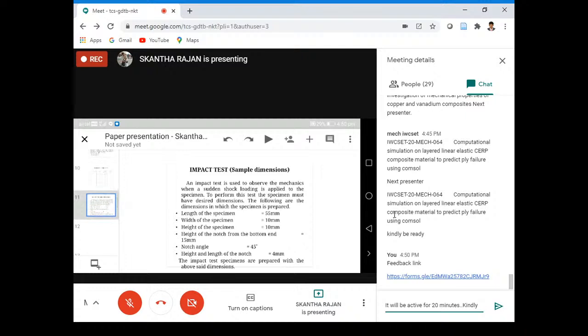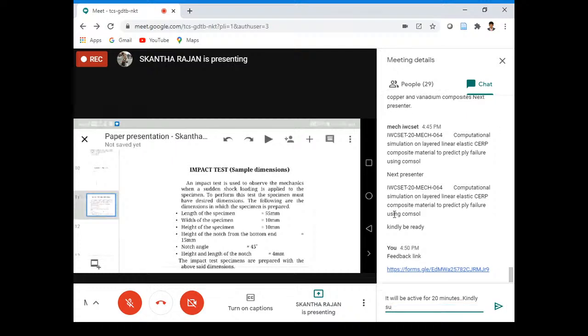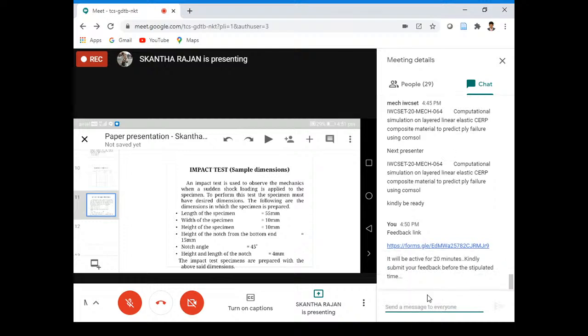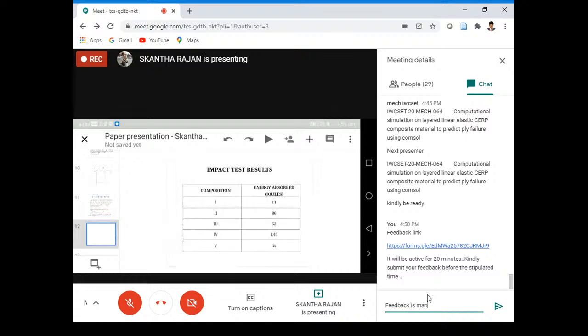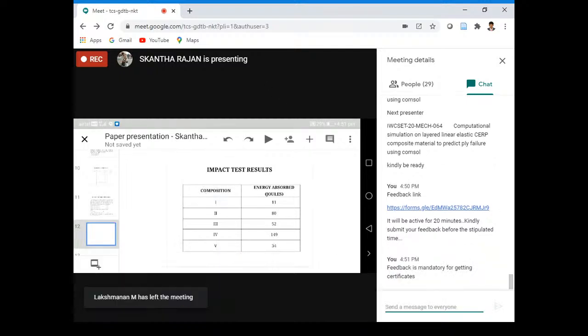You can proceed. Impact test. Next, we have done an impact test. The impact test is used to observe the behavior when a sudden load is applied to the specimen. In our project, we used the Charpy impact test. Before that, we prepared our impact test specimen. These are the dimensions of how we prepared our impact test specimen. These are the results we have obtained from our five different compositions. From this, composition 4 has better energy absorbed values.